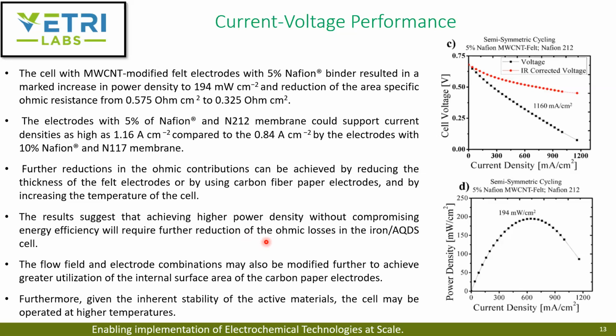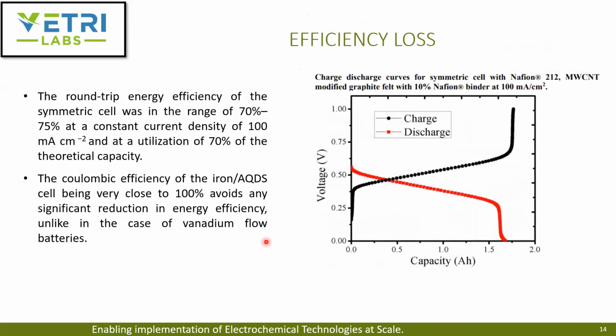And also the inherent stability of the active materials can be considered, and the cell can also be operated at higher temperatures. Regarding the efficiency loss, they identified that the round trip energy efficiency of the symmetric cell was in the range of 70% to 75% at a constant current density of 100 milliampere per centimeter square, and it is 70% utilization of the theoretical capacity. And the Coulombic efficiency of this Iron-AQDS battery was very close to 100%. So that tells that a significant reduction in energy efficiency is avoided, whereas it cannot be avoided in the case of vanadium flow batteries.